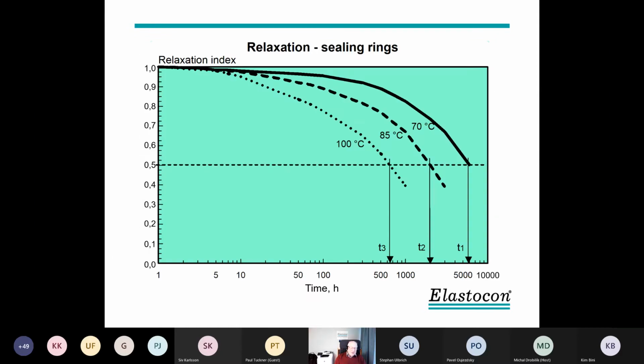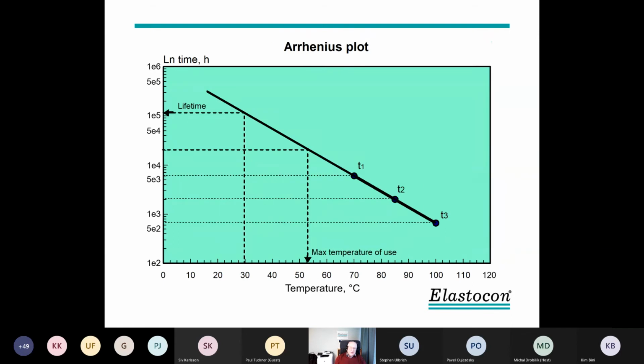Here we have still the same type of sealing rings, these SBR sealing rings. Tested at 3 temperatures, we found at 50% relaxation, we found 3 time temperature points, T1, T2, T3. And these were then inserted in an Arrhenius plot, which is a graph where we have on the x-axis down here 1 over absolute temperature in Kelvin. But we show Celsius here, we show better graphs later. And the time is shown on the y-axis in logarithmic time. So according to the Arrhenius formula, this should be a straight line. And then we can do extrapolation to a lower temperature.